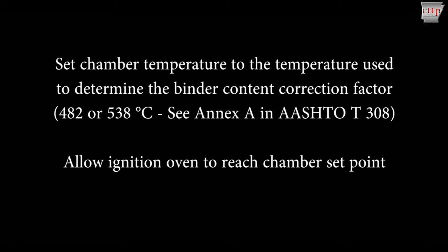Allow approximately 3 hours for the ignition oven to reach the chamber set point. Obtain a representative portion of the asphalt mixture and reduce it to the required sample size. Oven dry the sample at mixing temperature prior to testing, or collect a separate representative sample and determine the moisture content according to AASHTO T329. If the sample is not warm enough to separate, warm the sample at 230 plus or minus 9 degrees Fahrenheit until it is workable. Do not heat the sample for an extended period of time.